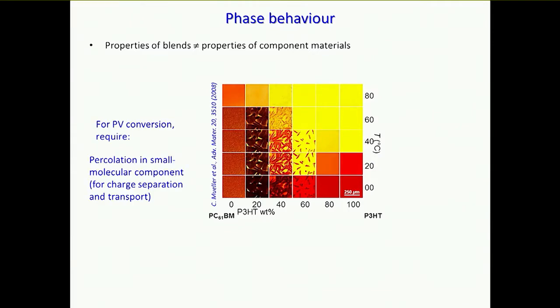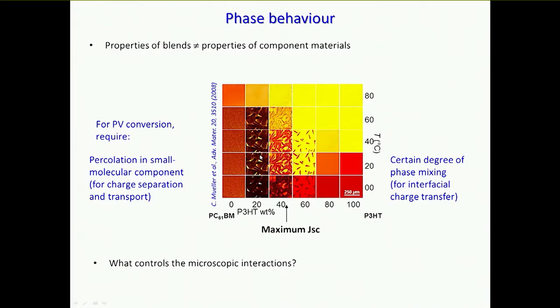If we think about what property of the blend we want, for example for a solar cell, we require a certain degree of percolation through the small molecular component, but we also require a certain degree of mixing. The consequence is that the optimum composition is slightly fullerene-rich relative to the point at which the interaction between the two components is the strongest, which we would call the eutectic point. To find this composition in another material system, we would need to understand what gives rise to those interactions that make the components mix and control the miscibility of one phase in the other.